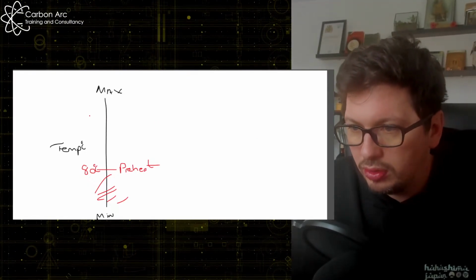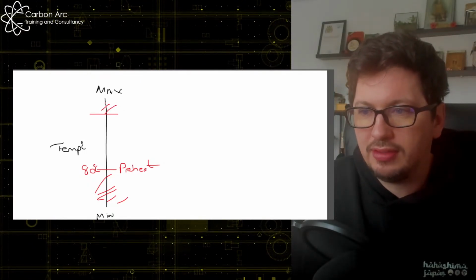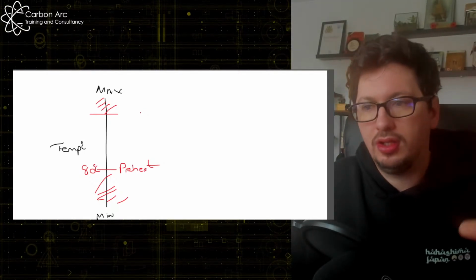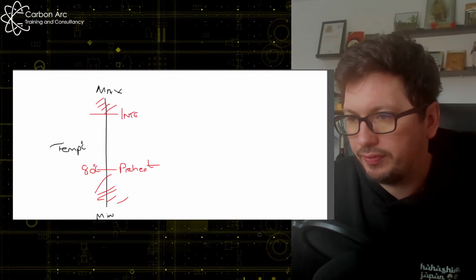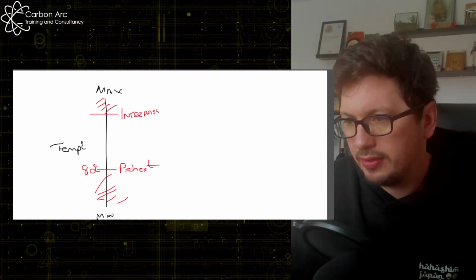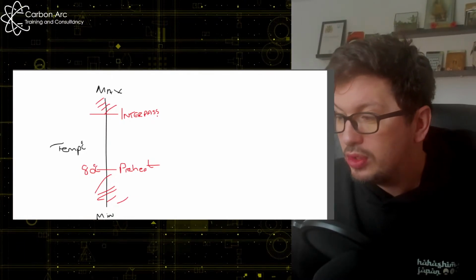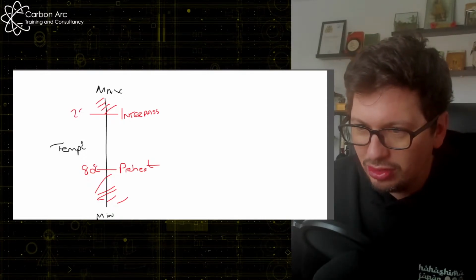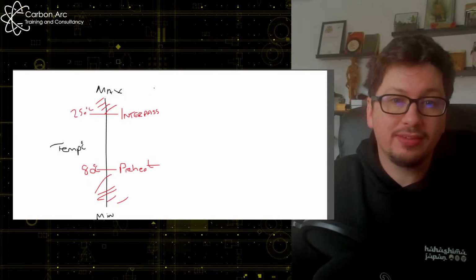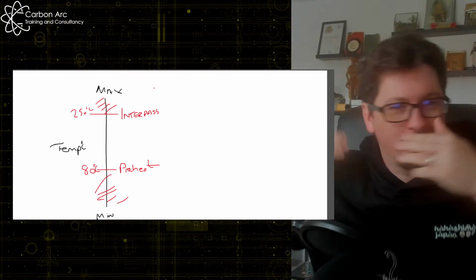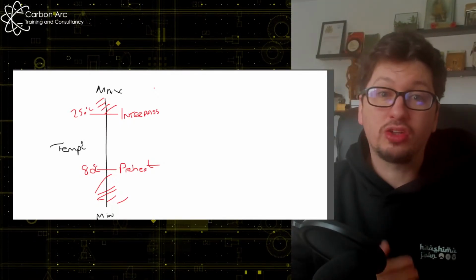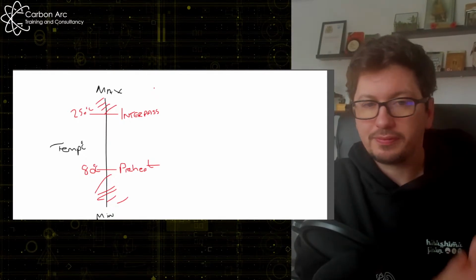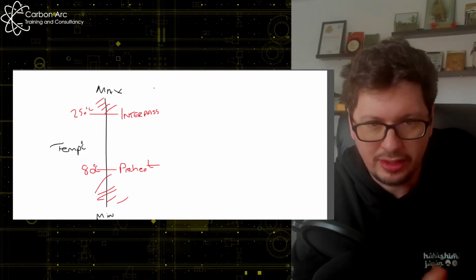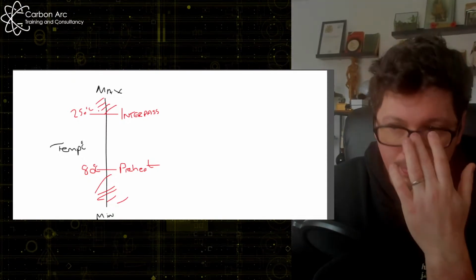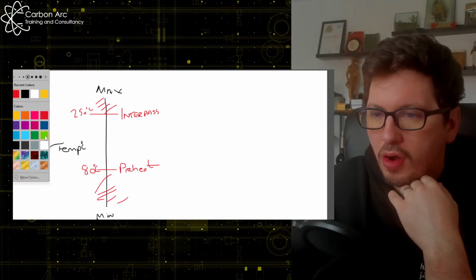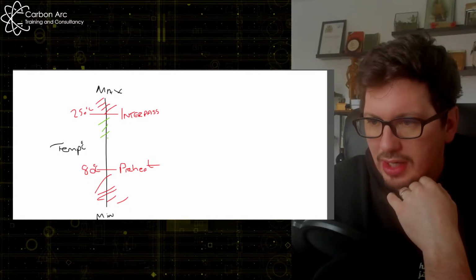So what we're then going to do is put a line across here and say anything above this line we're not allowed to weld. We have to let it cool back down to then weld. And this is our interpass. Now for carbon steel, when we don't know, we generally pick 250 degrees. You've probably seen that on a lot of WPSs. It's like, I don't know, I'm going to take a guess, 250 degrees. But in reality, that comes from the qualification sample. And then we get a range, like plus or minus 55 degrees Celsius, from whatever we tested in the PQR.